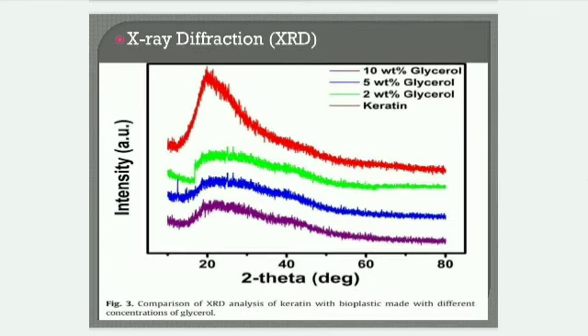X-ray diffraction, XRD. The figure shows peaks which indicate the strong crystalline characteristic. It is shown in the figure that bioplastic film synthesized with 2% of glycerol has the highest 2 theta value and the lowest d-spacing, which means it has the most ordered structure among the bioplastic films. Besides, bioplastic film synthesized with 5% and 10% glycerol showed almost similar results. It can be seen from the figure that strong crystalline characteristic was shown by the bioplastic film having the lowest glycerol concentration.